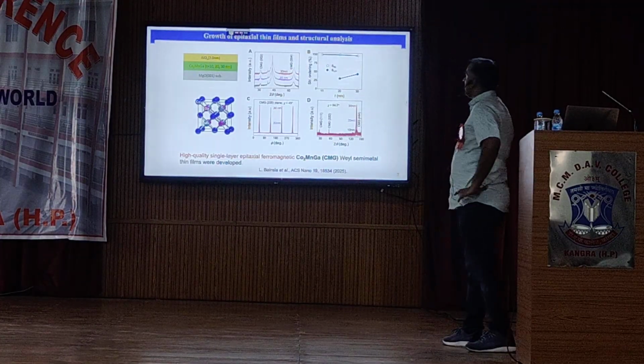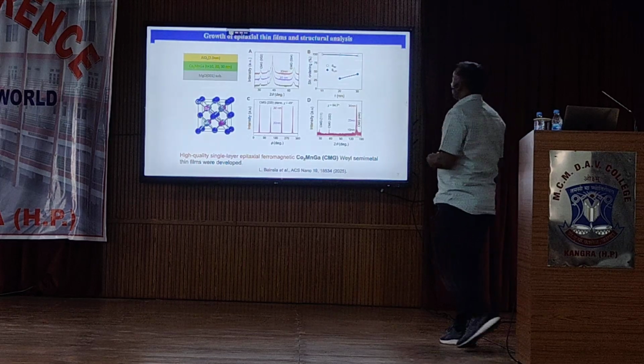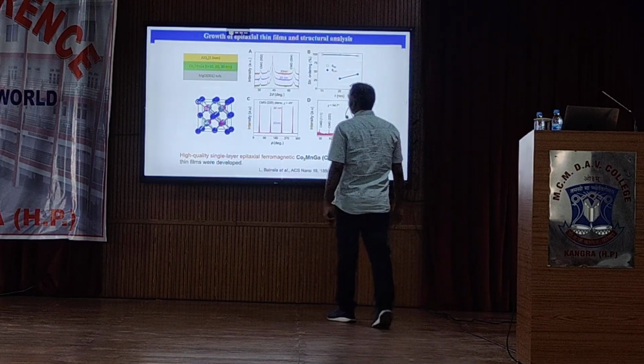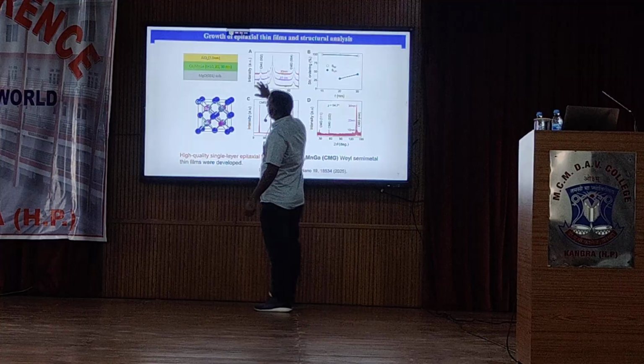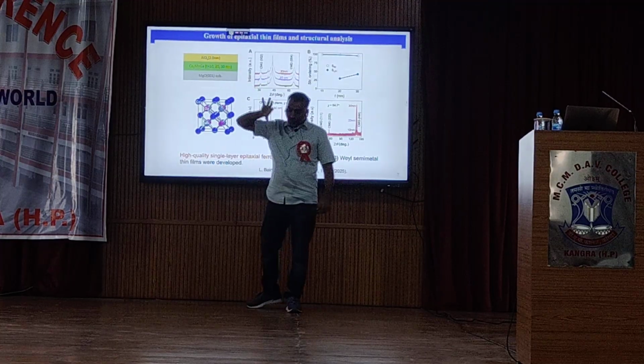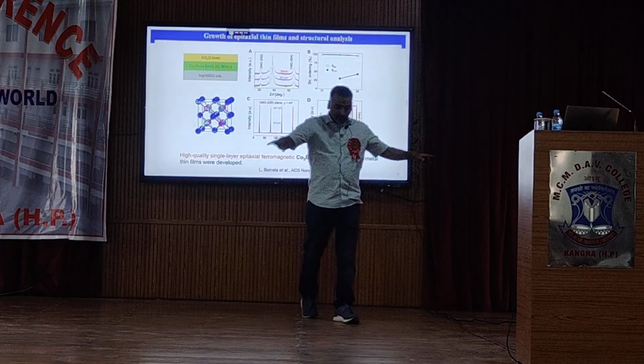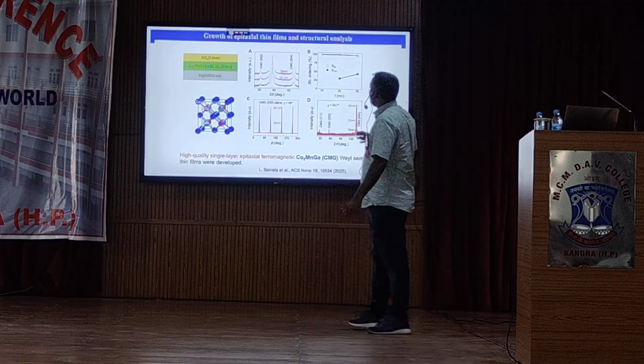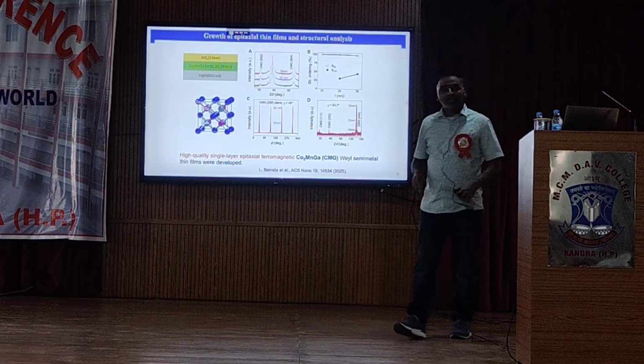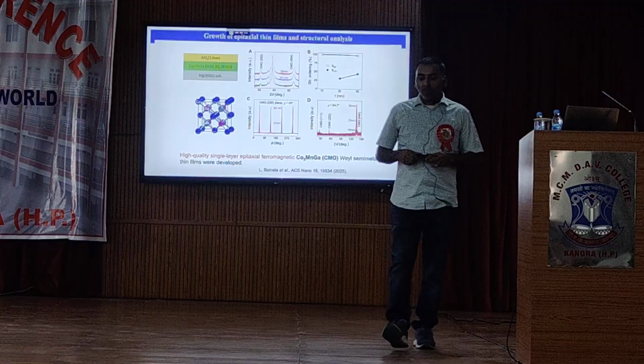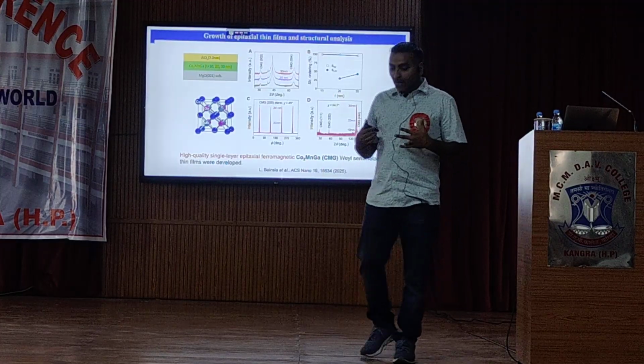So we first grow thin films of this material. In bulk form, this material, cobalt two manganese gallium, has very excellent properties because of its topological features like Weyl nodes and other surface states. But the challenge remains: can we sustain those properties in thin film form? So we started from slightly thicker thin films to see whether we can sustain those properties in thin